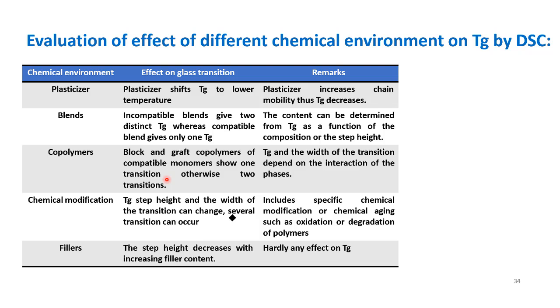Then chemical modification. The Tg, step height and the width of the transition can change. Several transitions can occur in the case of chemical modification. Then the filler. Again, with the filler, the step height decreases with increasing filler quantity, but the filler will not have any effect on the transition temperature.